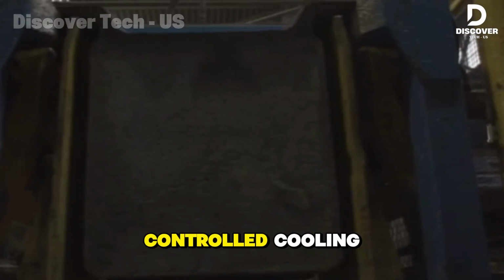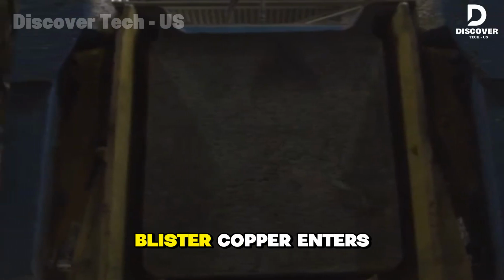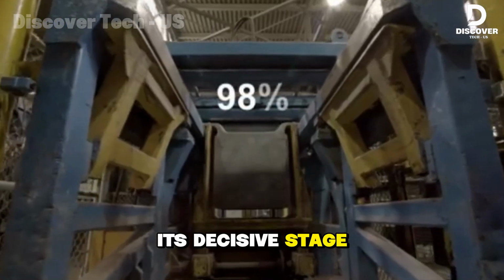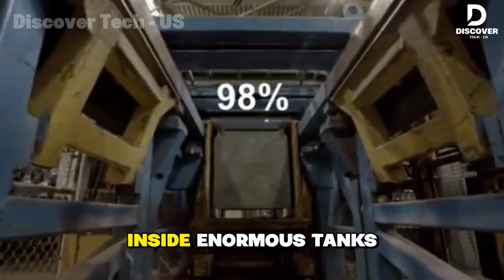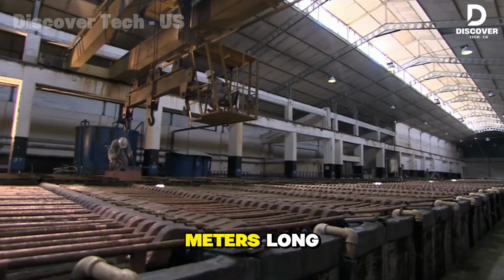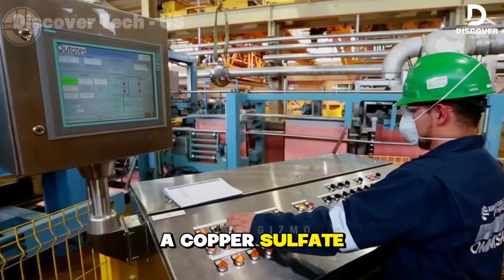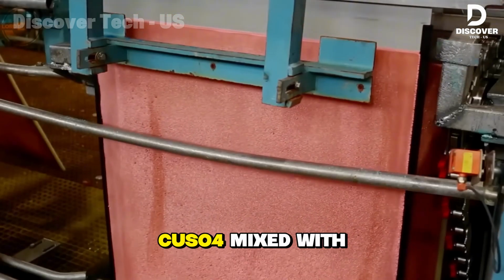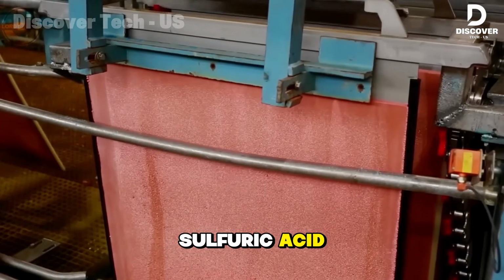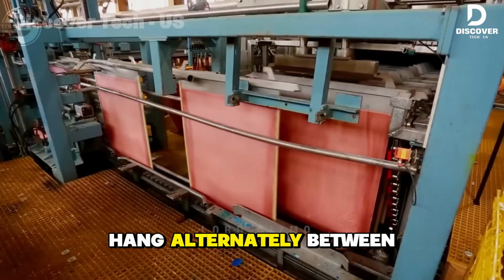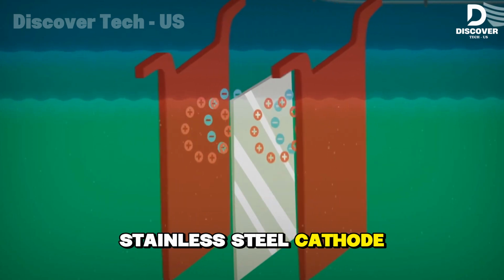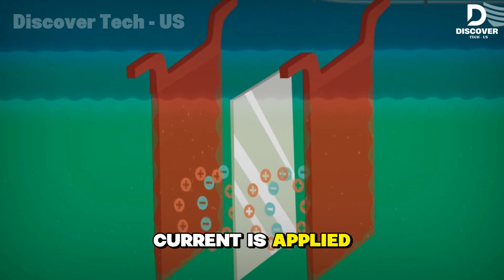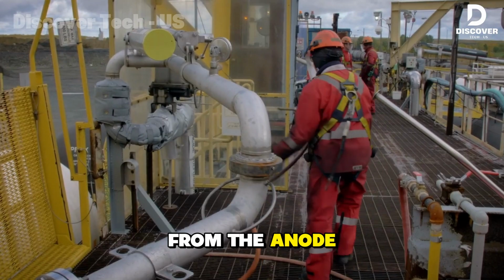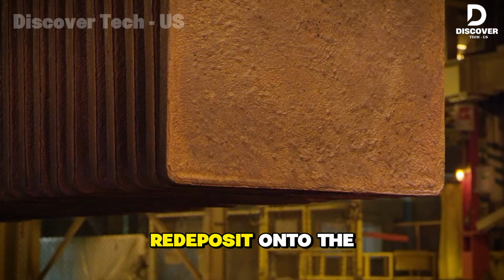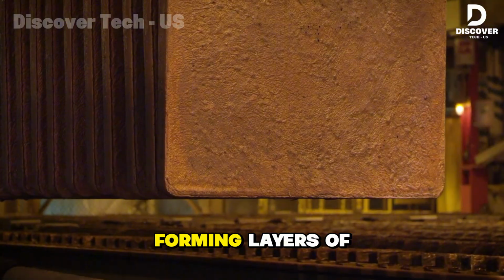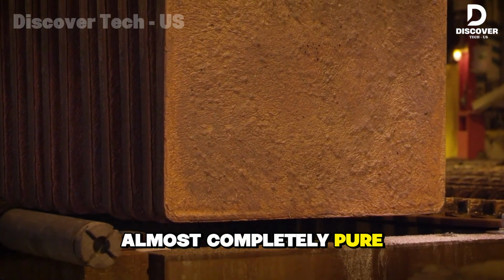After reheating and controlled cooling, the semi-pure blister copper enters its decisive stage, electrolytic refining. Inside enormous tanks stretching tens of meters long, each filled with a copper sulfate solution, CuSO4, mixed with sulfuric acid, blister copper anodes hang alternately between thin stainless steel cathode plates. When a direct current is applied, copper atoms dissolve from the anode into the liquid, then migrate and redeposit onto the cathode surface, forming layers of copper that are almost completely pure.